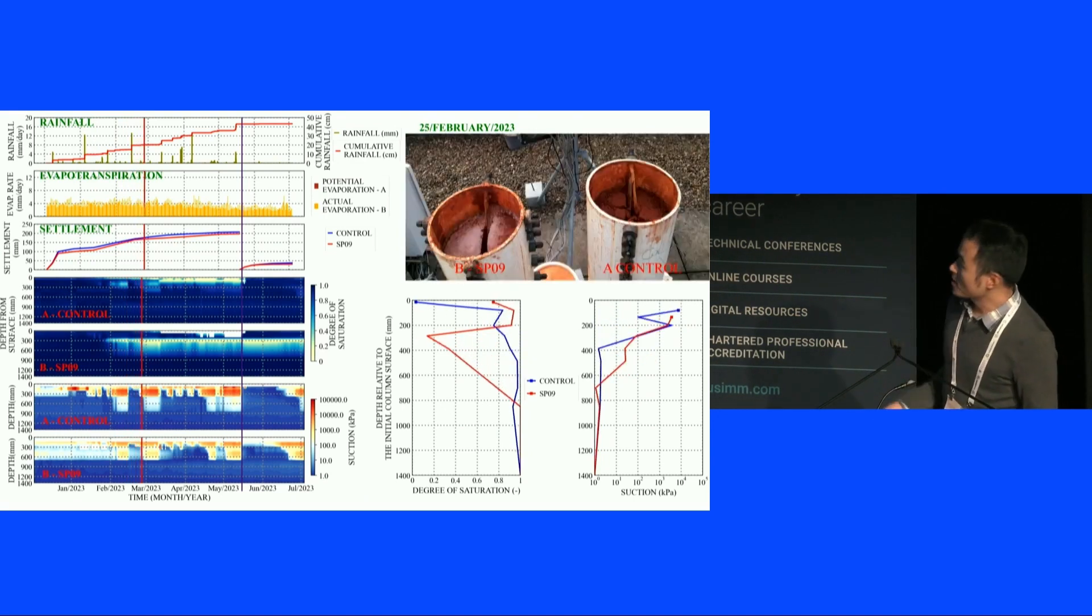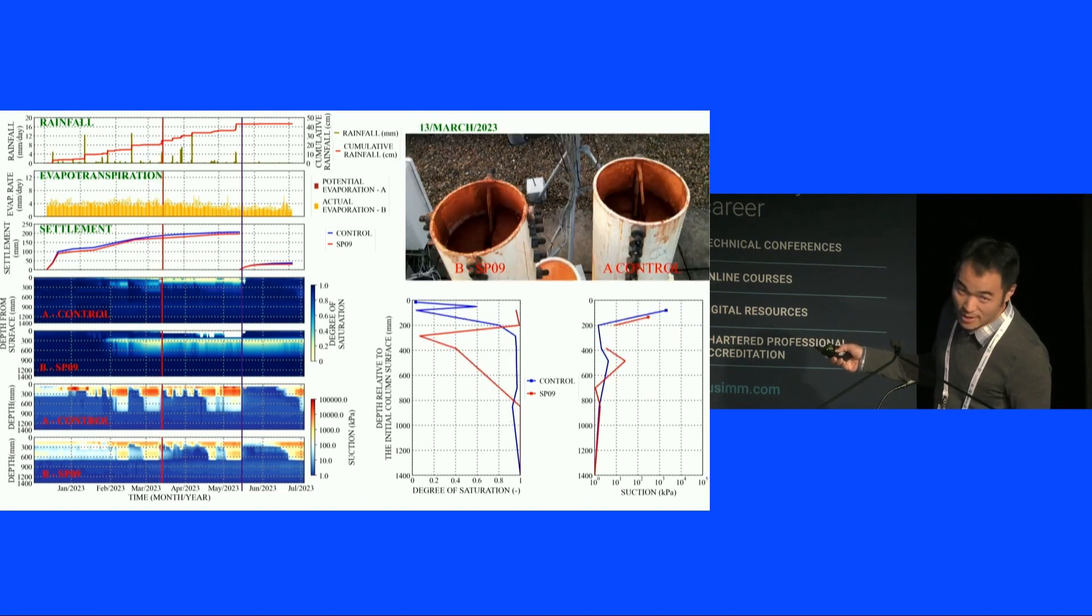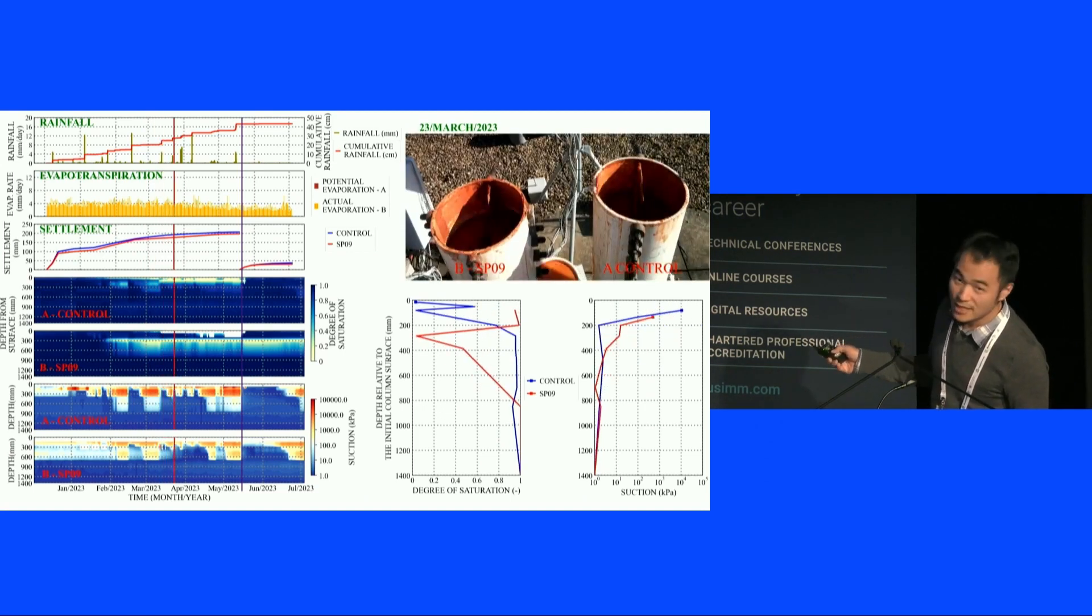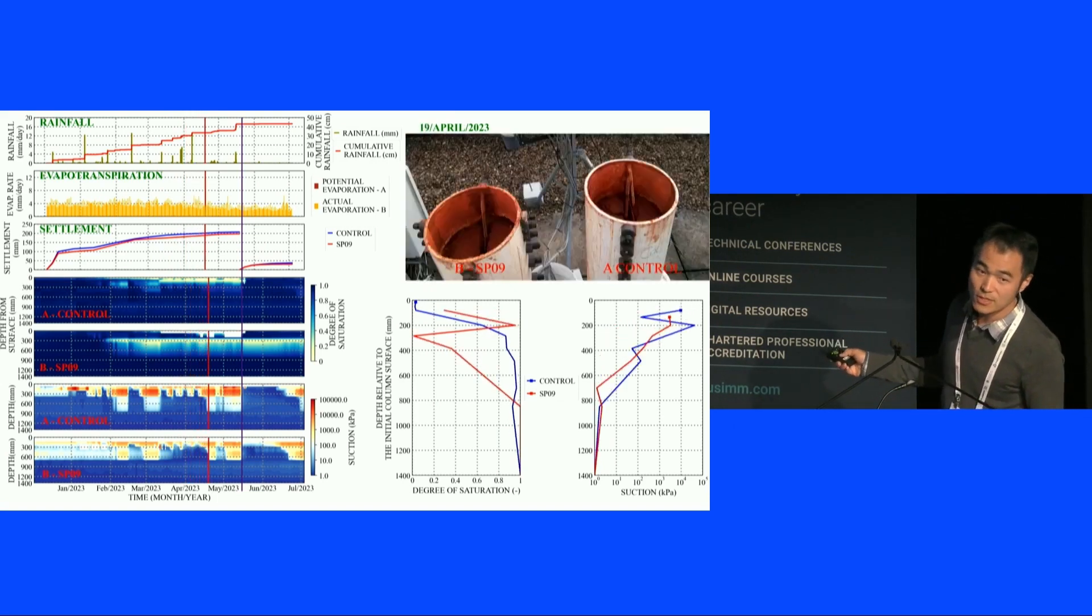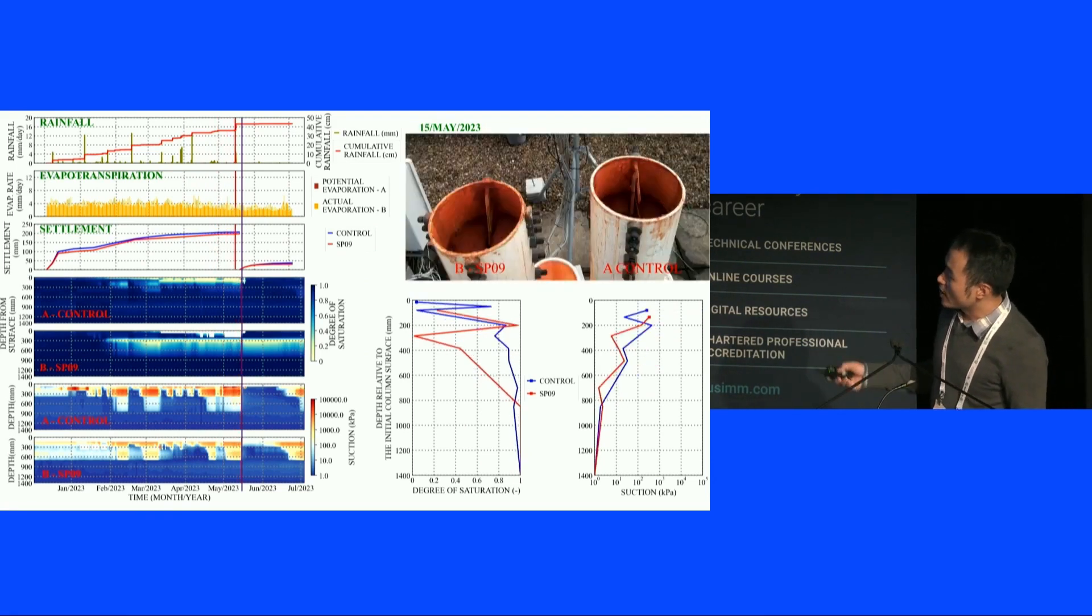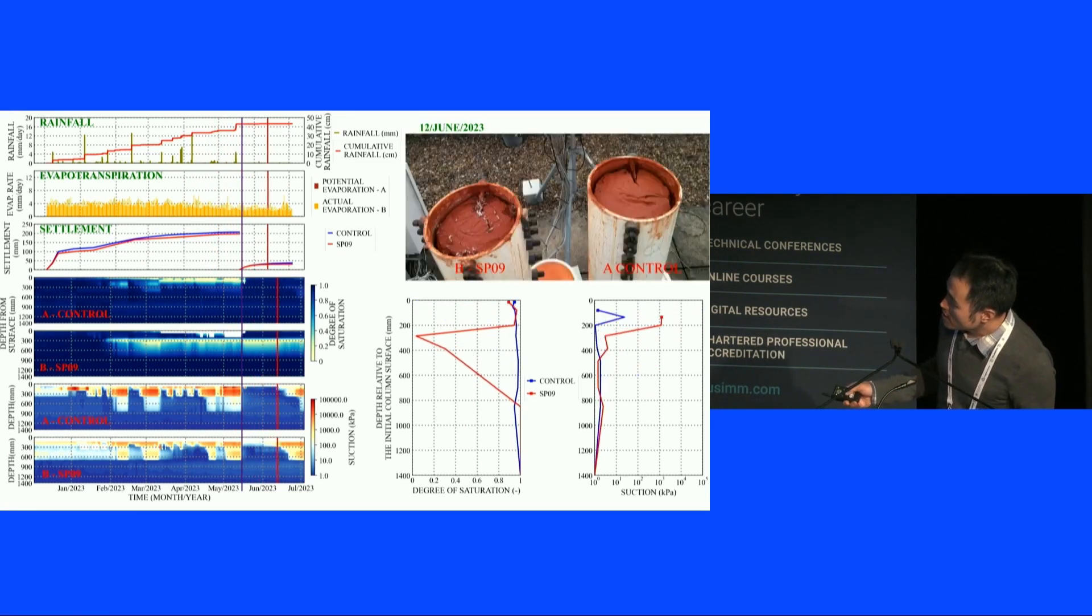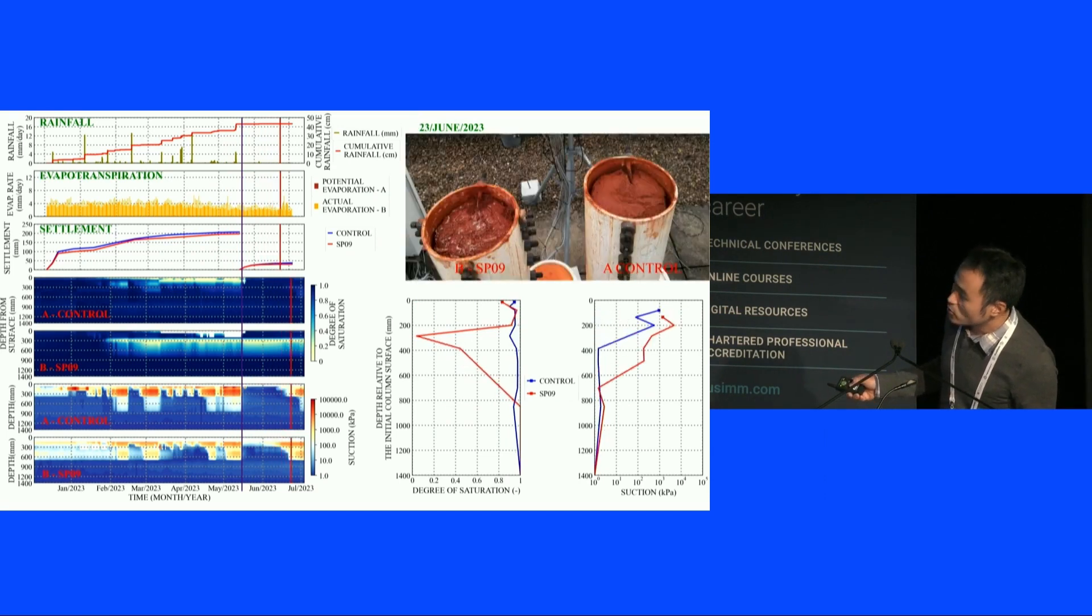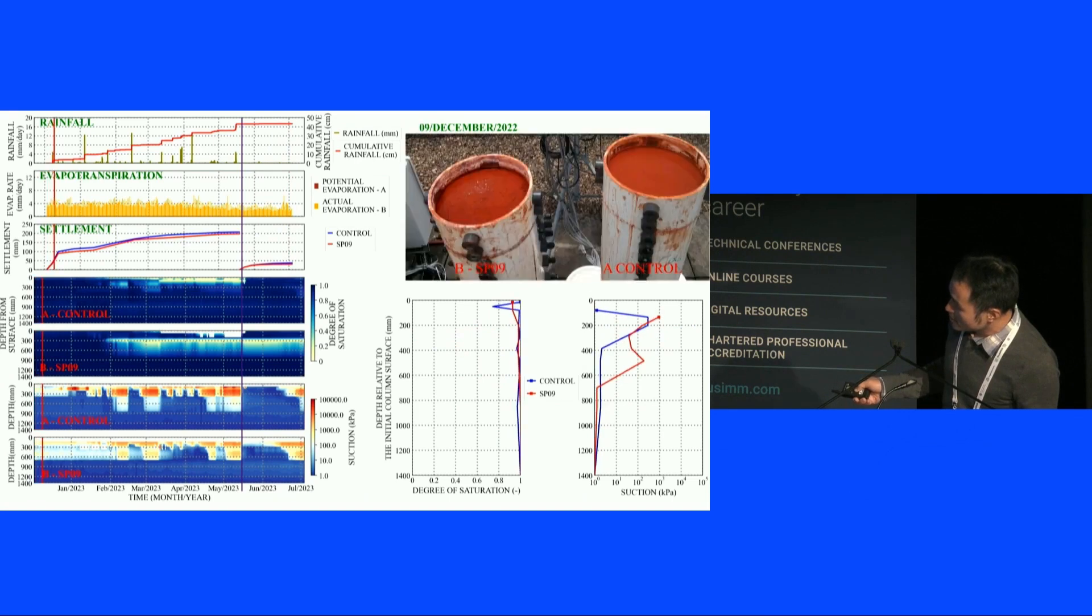The reason why I draw this vertical line here is because we actually add slurry tailings there to emulate a future deposition. And still, you see these two graphs are exactly the same. Key summary: 25% solids here, 45% solids there, and they settle in the same manner. So why is there no more water coming out from the 25% solids, given that they have more water there?